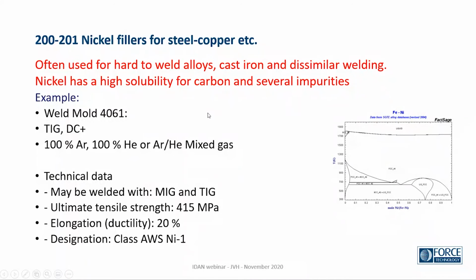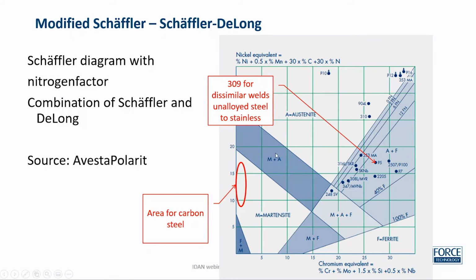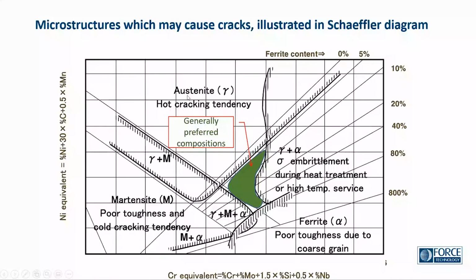And using nickel fillers is a choice for hard to weld alloys, cast iron, dissimilar welding, because it has this high solubility for, among others, carbon and the impurities. So a lot of the problems that we might experience from these combinations, we can solve by using nickel filler. But if we go back to this diagram, we would see that the nickel equivalent is high because it's directly related to the nickel content. We would be high up in this area, which means, if we go one step back further, that we have to deal with a high risk of hot cracks.